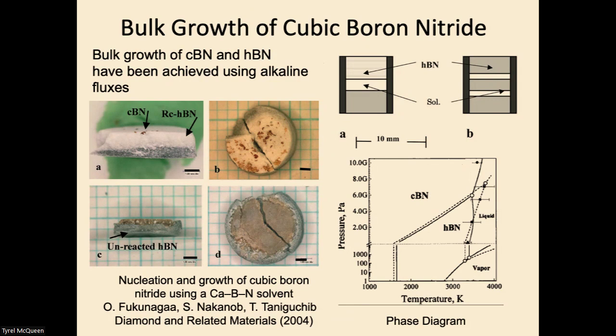So why can't you grow? I think your question is, why can't you grow cubic boron nitride at 1200 Kelvin? Well, I'm not sure the experiments have been done, right? We've all been trying to grow cubic boron nitride on diamond substrates. That's been the vehicle of choice. We haven't had to try to grow cubic boron nitride on a cubic boron nitride substrate as of yet.